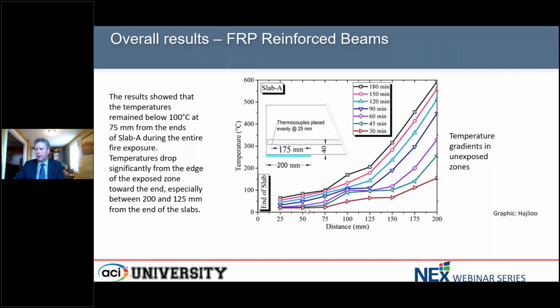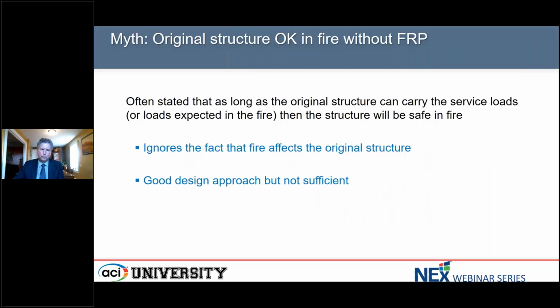And so you can see the temperatures remain below the glass transition temperature in this region. And so that was quite important to have those to be able to anchor the bars into relatively cool areas of the concrete.